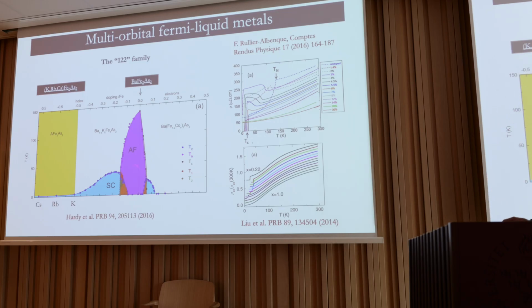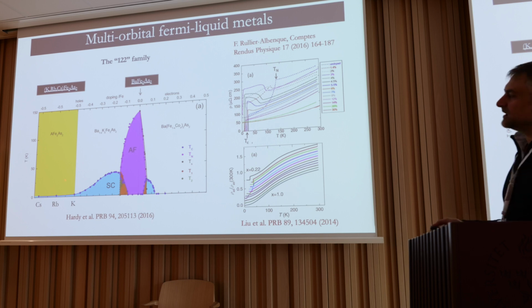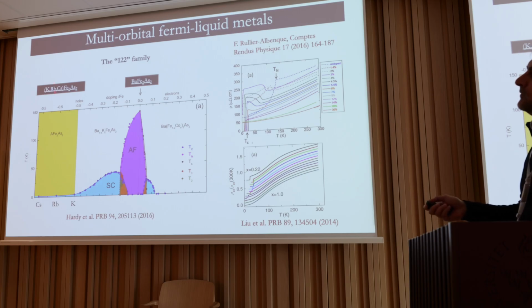You can synthesize a lot of compounds, and you can even get to the stoichiometric case in which you have fully replaced barium for potassium, so you have potassium 1-2-2, but you can even further substitute isovalently with rubidium and cesium. Superconductivity does not really go away, but it becomes small. However, what goes away is this magnetic collinear stripes.